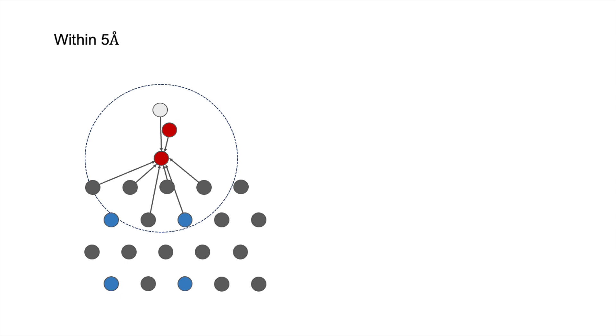Now this works in most cases, but there can be edge cases where this isn't ideal. For instance, if the adsorbate's really far off the catalyst surface, and you set a cutoff at five angstroms, it's possible that the cutoff might be too small and never actually include any of the atoms of the catalyst. And then if you do this, you'll never actually see the attractive forces of the catalyst on the adsorbate.